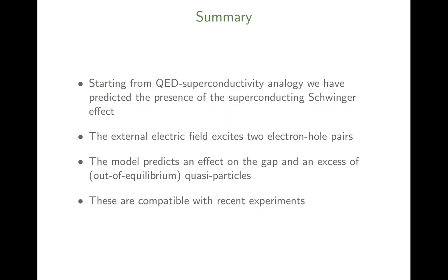And we have found that the electric field excites electron-hole pairs. And these electron-hole pairs are responsible, at least in simulation, for the weakening of the superconducting energy gap in a superconductor. And we have provided some intuition that this might be compatible with some recent experiments where they were seeing the lowering of superconductivity due to a strong external electric field. And I thank you for your attention. Thank you.